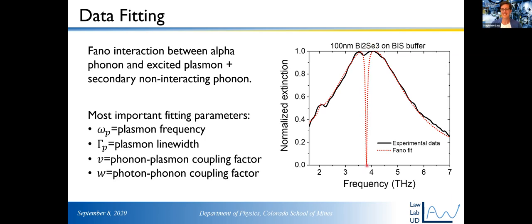But you can see that actually the fitting does work really well. We have this nice fit. And from this fitting, we can extract a variety of parameters, including the plasmon frequency, right? This is what we want. We want to map the dispersion of this mode to prove that it really is a Dirac plasmon polariton and just to understand the excitation, right? That's how you fundamentally understand something, is by measuring its dispersion.